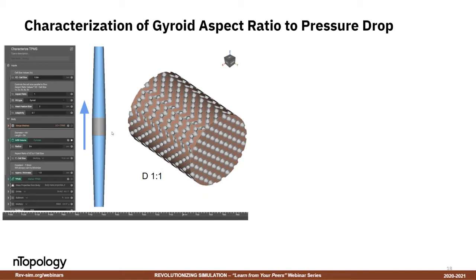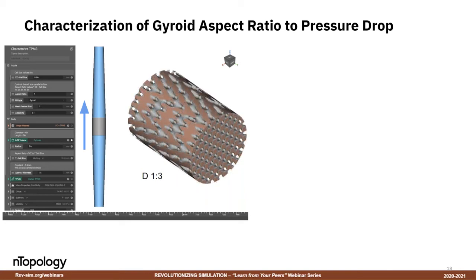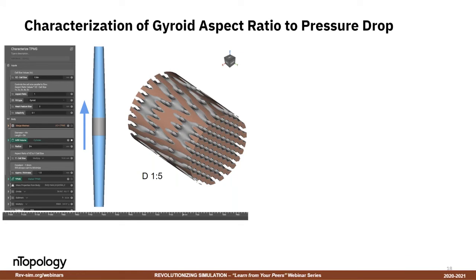In this scenario, the cell size that defines the structure or shape is 1-to-1, meaning that the cell size in the X and Z axes are the same as in the Y. Now what we're going to start to do is stretch that cell size in the Y direction, or you can think of it as the direction of flow. So now we have an aspect ratio of 1-to-5 with the gyroid structure.